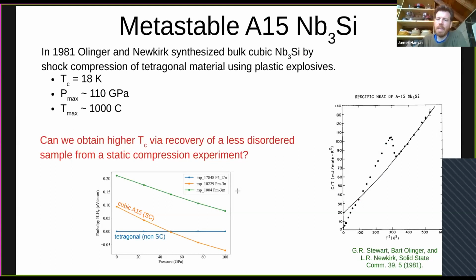And specific heat measurements showed a very nice specific heat transition, but the TC here was around 18 Kelvin. So again, the prediction was that it could be up around 25 or 30, but it was instead down around 18. And so the question was whether we could obtain a higher TC by recovering a less disordered sample from a static compression experiment. So this shock compression is very violent. Could we do a better job with static pressure? And some computational results showed that this cubic A15 phase should become stable above about 15 GPa.